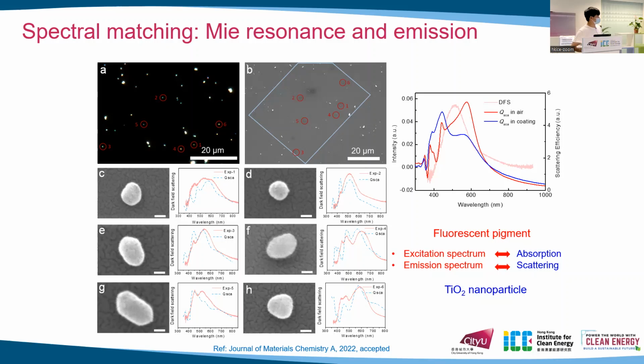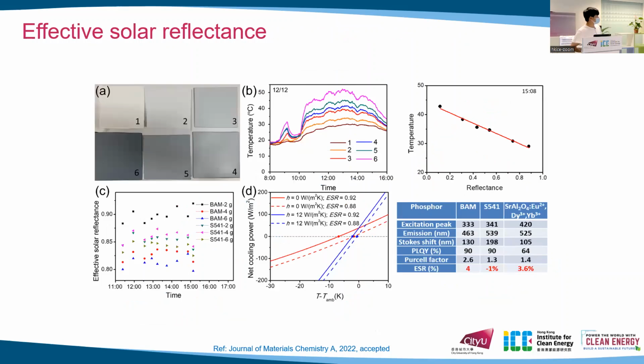First, we should match the excitation spectrum of the phosphor to the TiO2 nanoparticles' absorption spectrum. And then we should match the emission spectrum of the phosphor to the scattering spectrum of the TiO2 nanoparticles. After that, we want to evaluate how this Purcell enhancement can improve the solar reflectance.